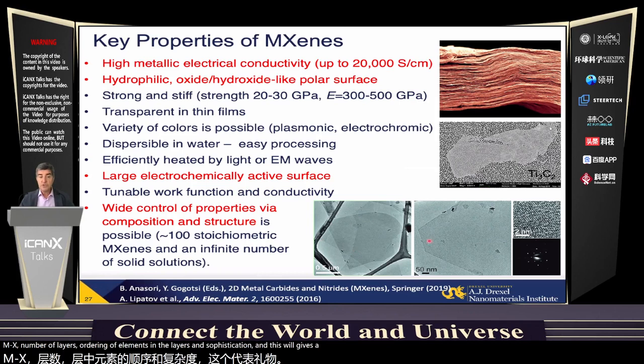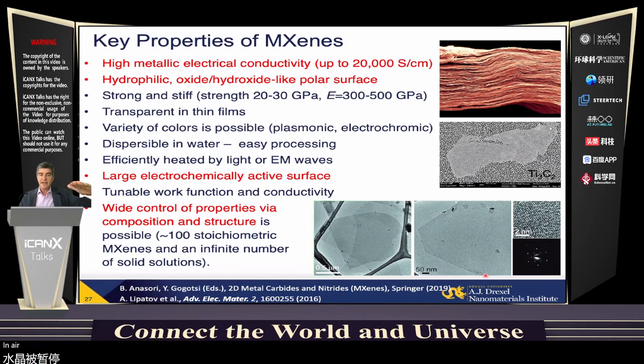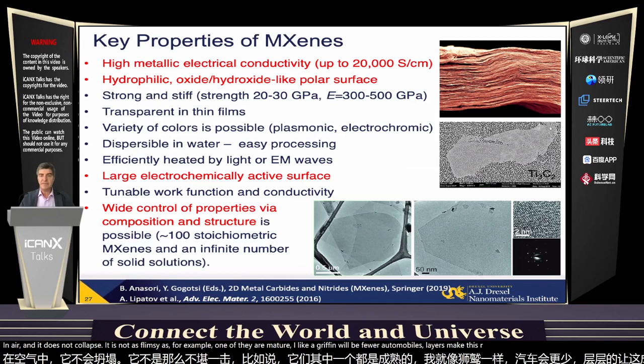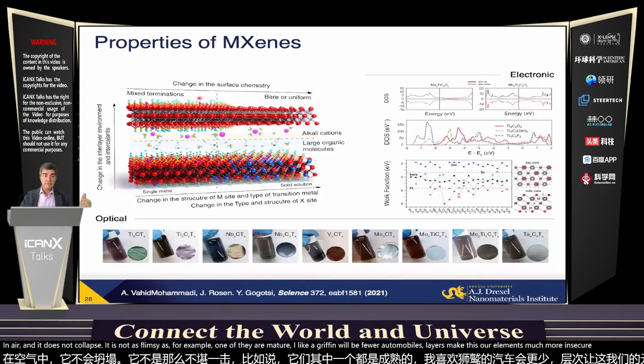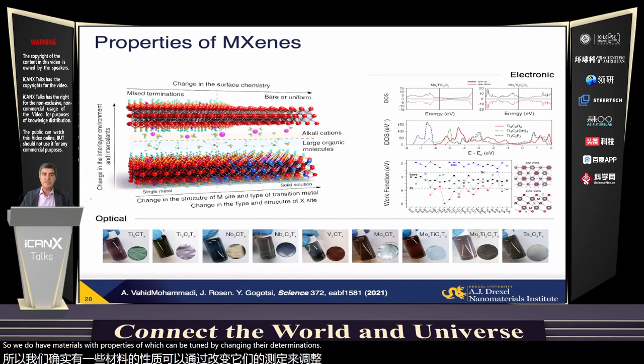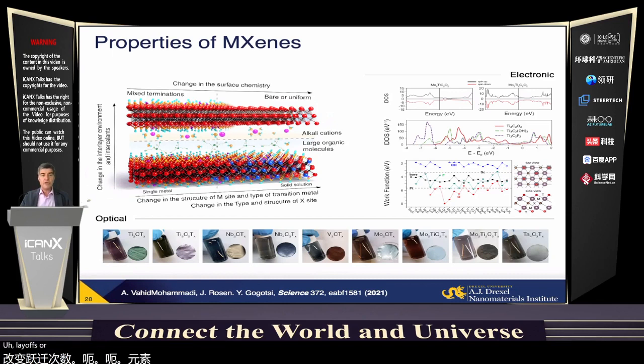But keep in mind, those are still single crystal layered particles. They have an ordered structure. You can see electron diffraction from a single flake. And you may remember I stressed the importance of having more than a single layer. This flake crystal is suspended in air, and it does not collapse. It is not as flimsy as, for example, a monolayer material like graphene would be. A few atomic layers make these elements much more rigid here. So we do have materials whose properties can be tuned by changing their terminations, changing the number of transition metal element layers, or ordering of the layers here.